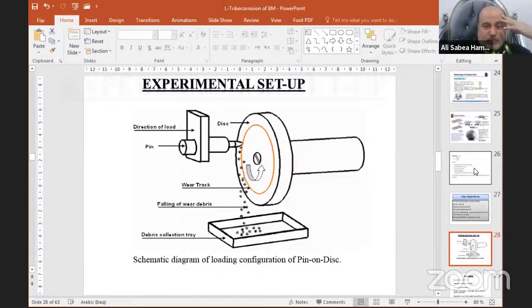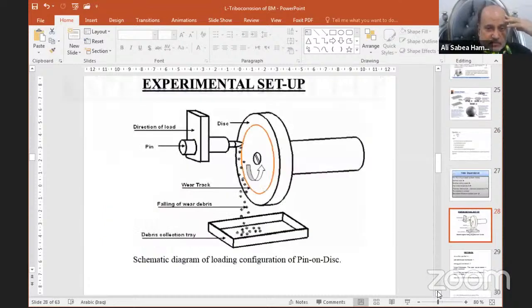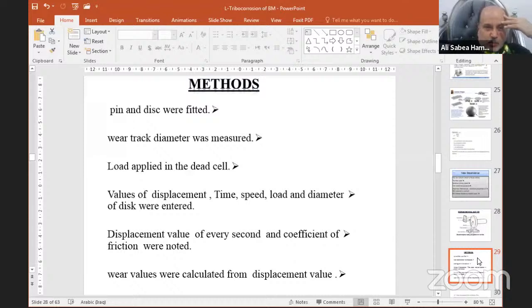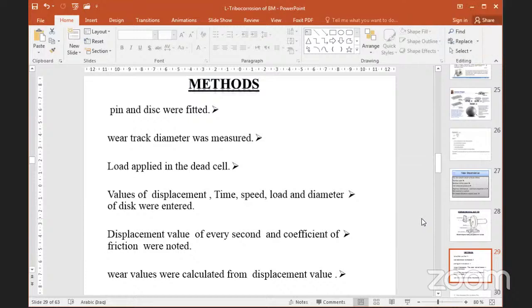This is the experimental setup for pin on disk. It shows the schematic diagram of the loading configuration of the pin on disk method. The pin and disk were fitted, the track diameter was measured, and the load was applied through the dead cell. Values of displacement, time, speed, load, and diameter of the disk were entered for determining the wear rate. For determination of wear rate, the displacement value every second and the coefficient of friction were noted, where values were calculated from the displacement value.